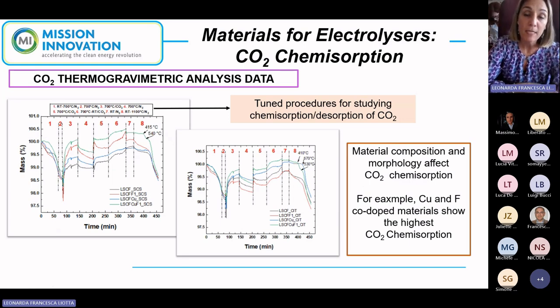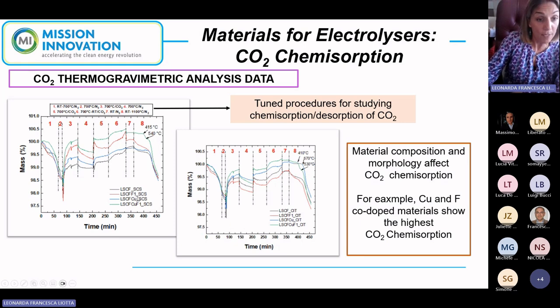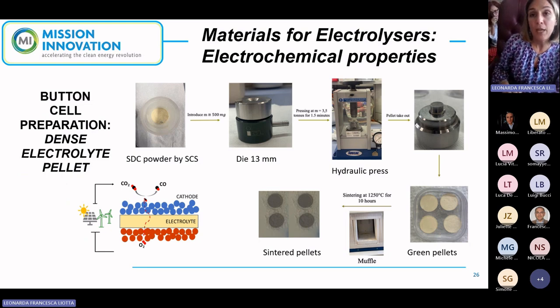Materials must be able to chemisorb CO2. In our lab, we are able to test these properties by thermogravimetric analysis in CO2 at different temperatures, and also by changing the cycle of chemisorption and desorption. We report here the data for the samples differently doped and also prepared by solution combustion synthesis and the citrate assisted method. In both cases, the co-doped samples exhibit the highest CO2 chemisorption capability. In general, material composition and morphology affect these properties. Finally, in our lab, we are able to test the electrochemical properties of the materials.